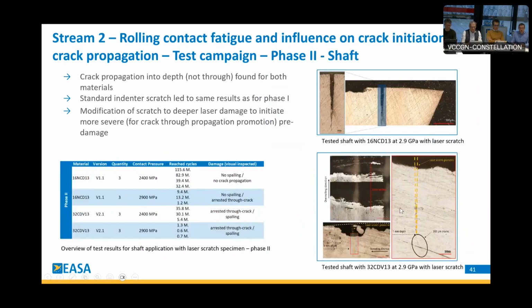And then we went on to phase 2. For phase 2, the complex loading, we started with the shaft testing. For the shaft, first of all, we did find crack propagation into the depth, but not through the part. Yes, in depth, but not through the part. We first started with the standard indenter scratch, as mentioned before.